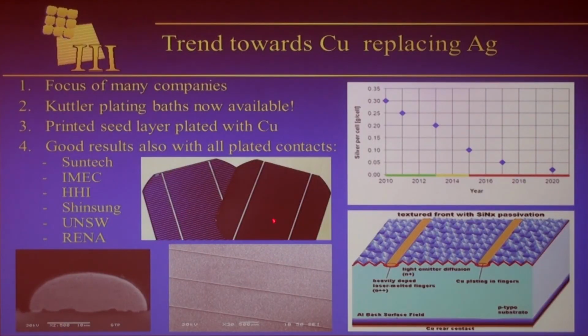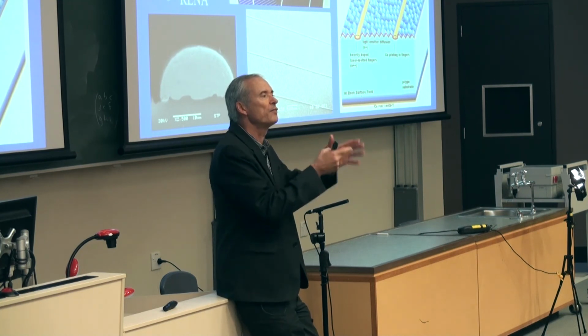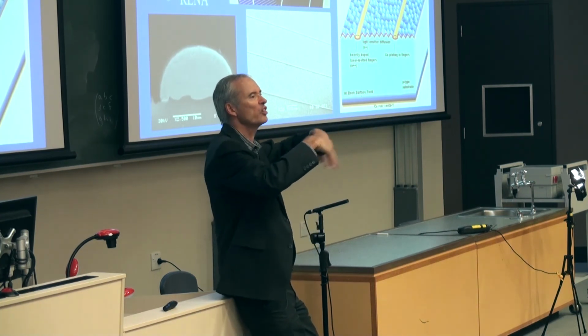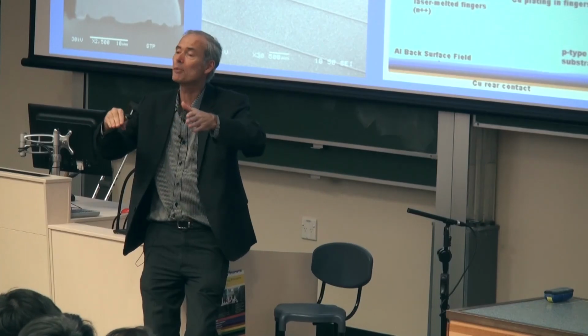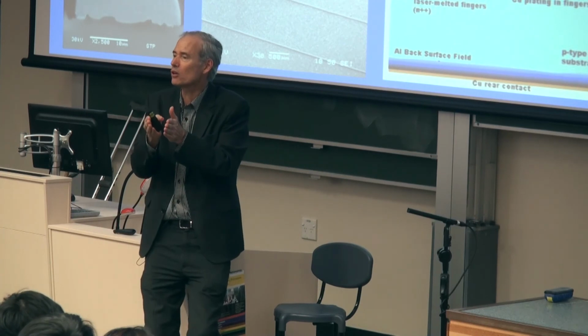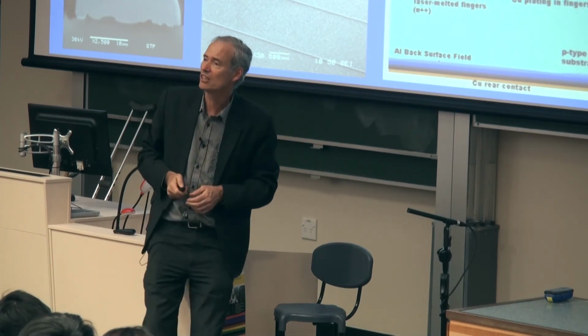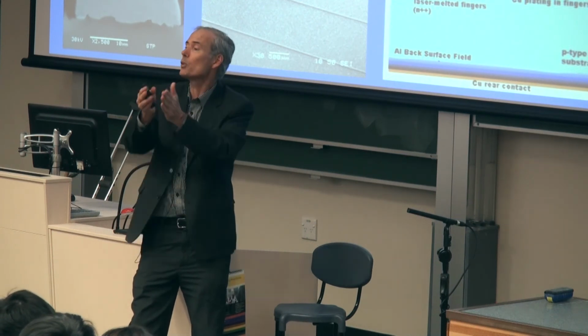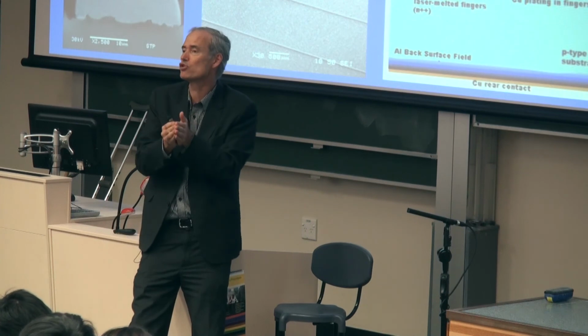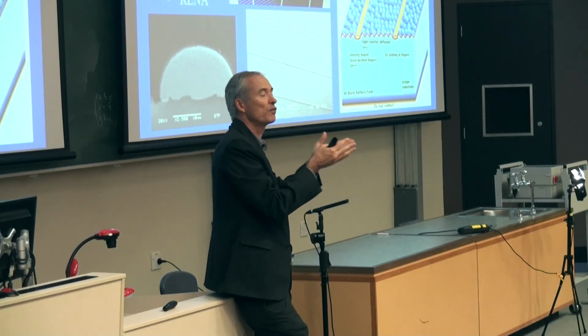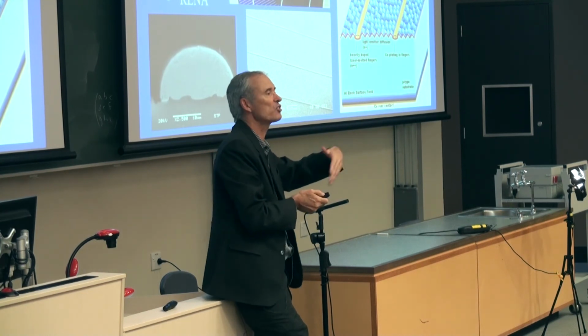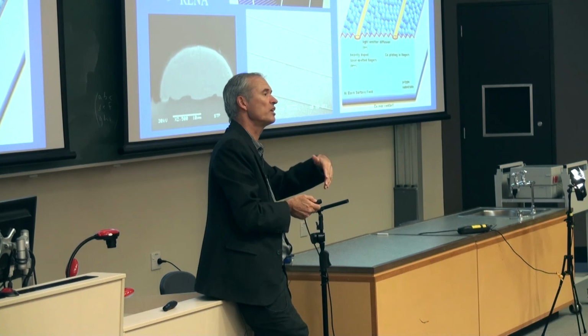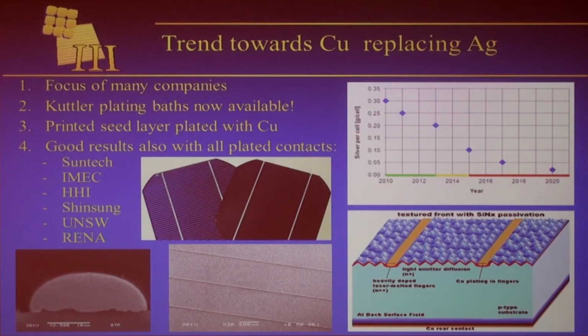This shows you the difference between two solar cells. This one's got the silver, this one's got the copper lines. Because one of the advantages of doing plated contacts is you tend to be able to make them a lot narrower than if you're trying to screen the metal onto the surface. Screening is very simple, low cost, it's a great, reliable process, but it is a challenge to make the metal lines really narrow. Whereas with a plated technology, all you need to do is pattern your dielectric, and as narrow as you can pattern your dielectric, you can just plate to the exposed region and very simply produce a metal contact of whatever width you want. And patterning the dielectrics is very easy these days. You can use lasers to do it, you can use inkjet technology, there's a range of approaches that you can use.